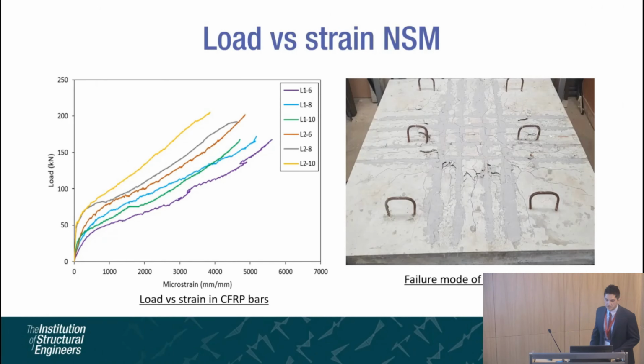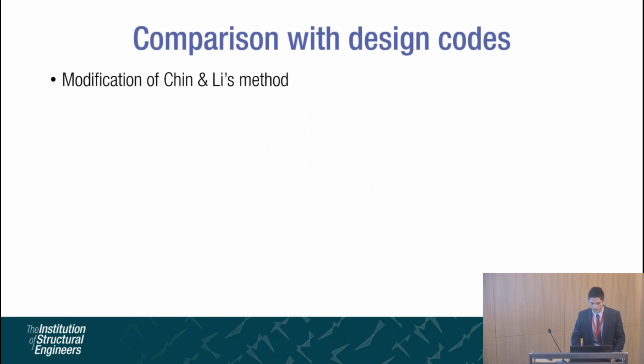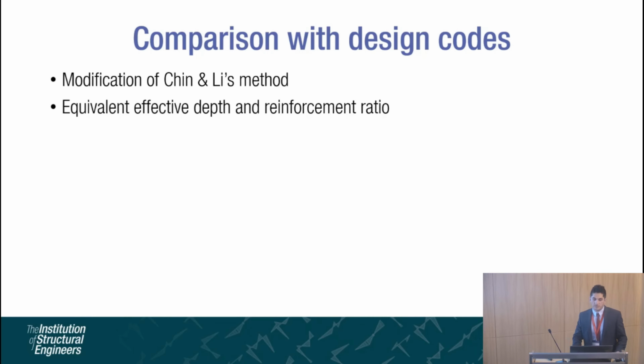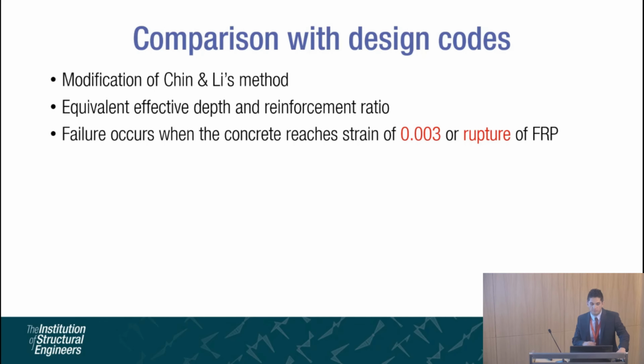The load versus strain graph is shown, and the strain level is much higher as compared to the EBR method, which contributes to the increase in load. So these experiments are compared with the design codes. The design codes do not provide definitive guidance for strengthened slabs, but we use a method developed initially by Chin and Li. It basically introduces 2 new terms, called effective depth and effective reinforcement ratio. Failure occurs when the concrete reaches a strain of 0.003 or when the FRP rupture occurs, whichever comes first.